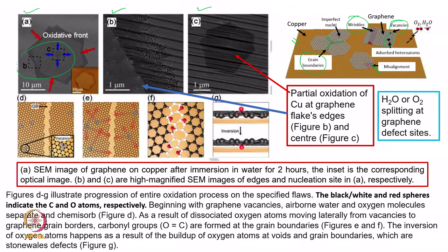Figures B and C are shown side by side, with B displayed in a zoomed or magnified form. B is at a 1-micron scale, and C is also at a 1-micron scale. B shows corrosion of copper, while C shows the patch where graphene was residing or was capped on the top surface of the copper. Bringing some sort of impurity provides a path for the electrolyte or conductive path, which creates corrosion — this is partial oxidation of copper at the graphene flake's edge.